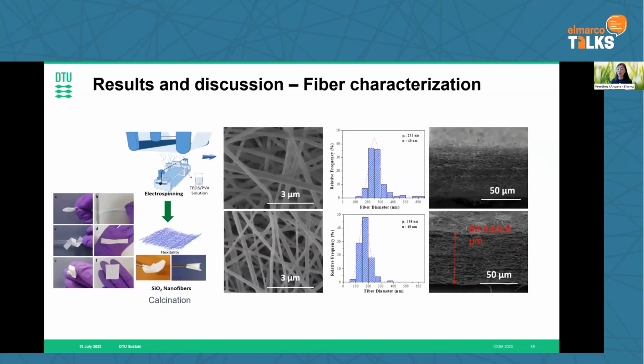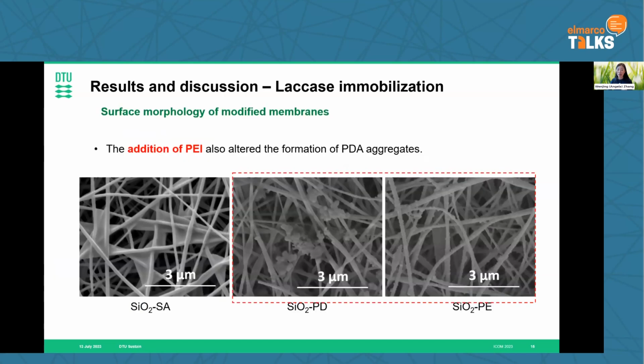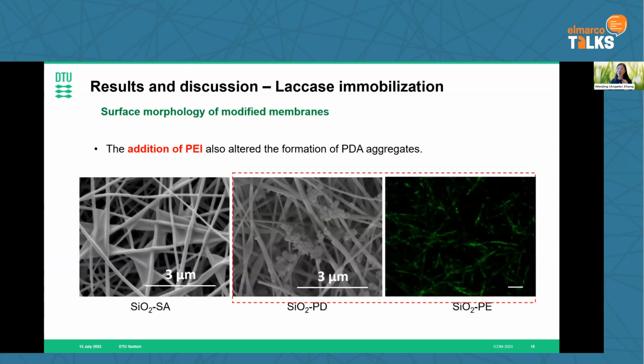So first we can see those ceramic membranes are flexible. That's quite different from our common sense about ceramic. They're rigid and quite bulky as well. Here it is like a piece of cloth, and it is ceramic, with a fiber diameter of about 200 to 300 nanometers and a thickness of about 50 micrometers. And then we functionalize those nanofibers, and we also put the enzyme. By confocal microscope, you can see those grains, the shining light indicates enzyme presence in our nanofibers.